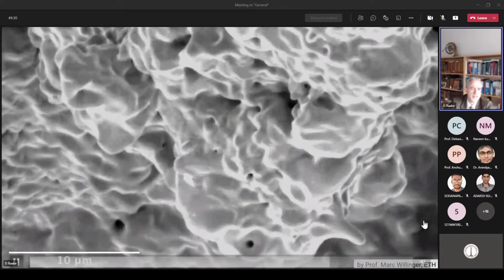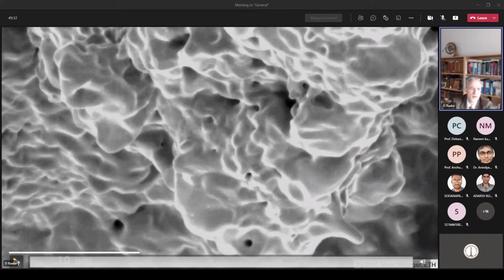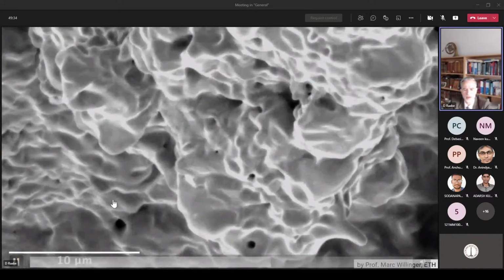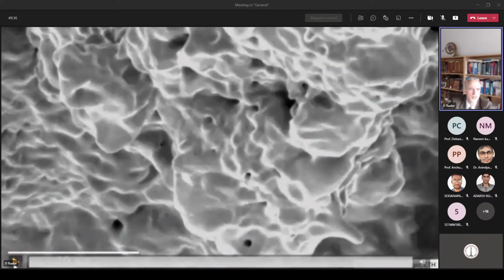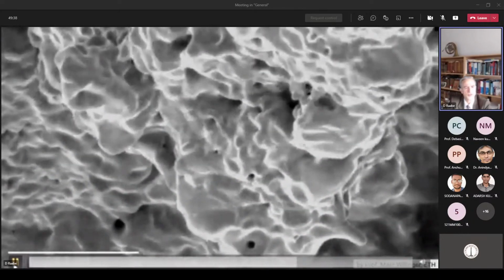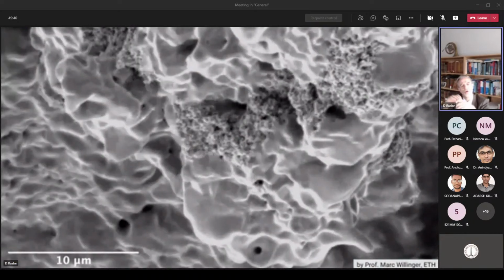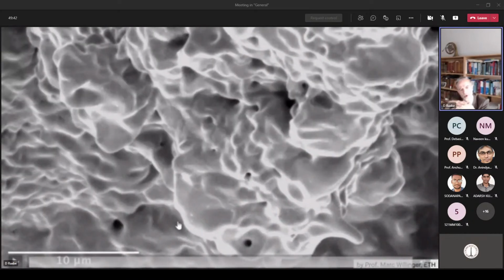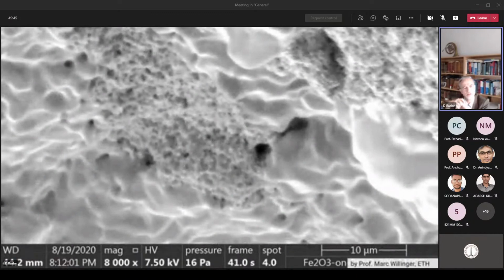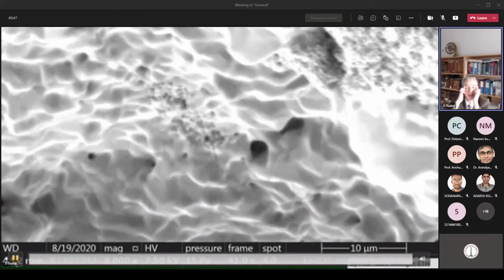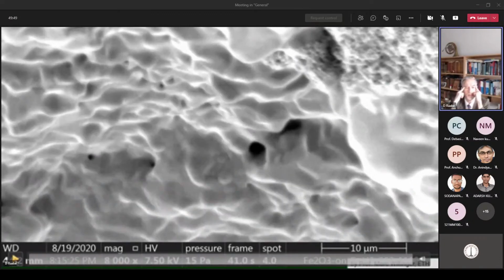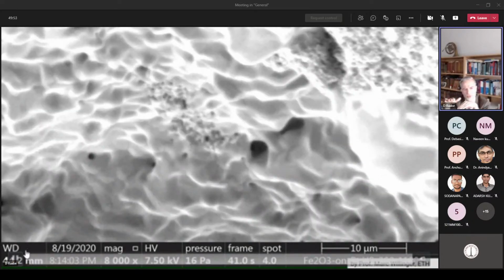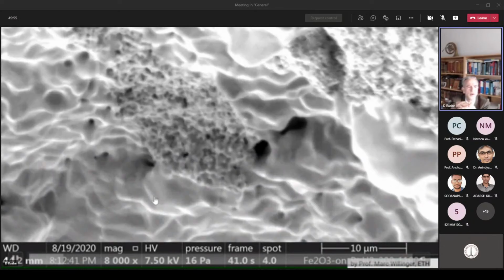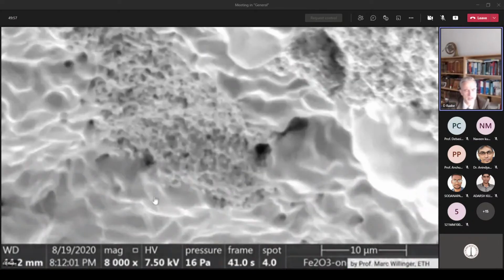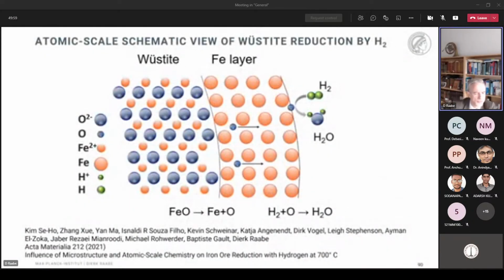Now here you can see a very nice environmental movie, taken in an environmental electron microscope by my colleague Professor Willinger at the ETH in Zurich, in Switzerland, where you see how the iron is growing on top of that oxide. Here's another movie with slightly higher resolution, where you see that the rough surface is the oxide, but the iron that forms of course on top where the reaction is taking place, and the mass transport is really fast.